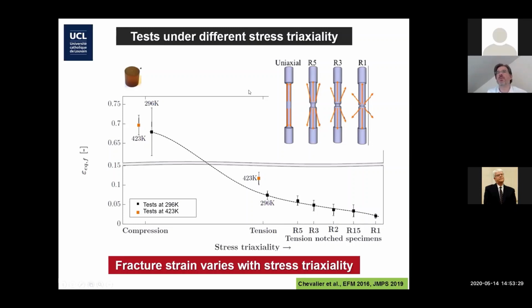But we perform tests on notch specimens, shear specimens, compression specimens on RTM6. This is the fracture strain, the true equivalent fracture strain under different stress triaxiality from compression, shear, and I forgot to put the point with shear, but there should be another point for shear here, uniaxial tension, different notches, and different temperature. And you see a clear effect of stress triaxiality. So if you want to develop a micromechanical model, it should be able to capture a trend like this.